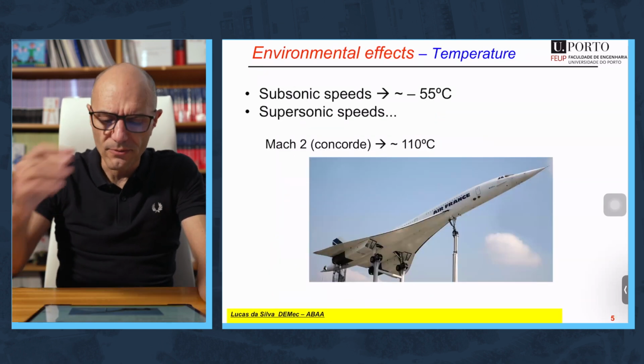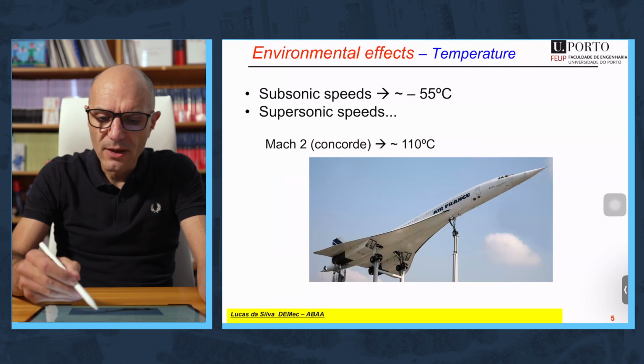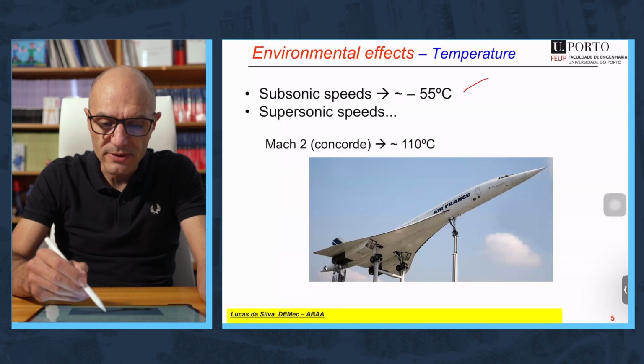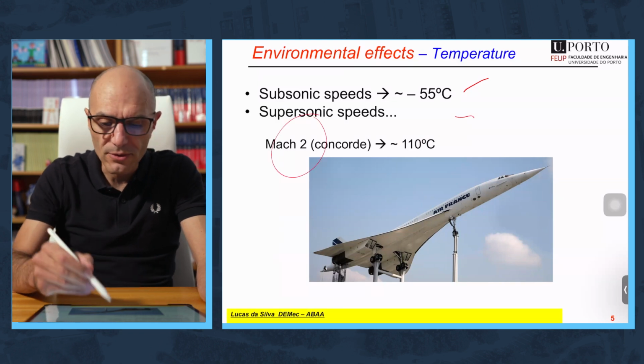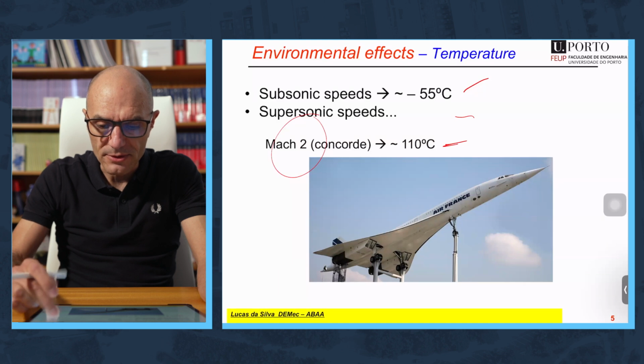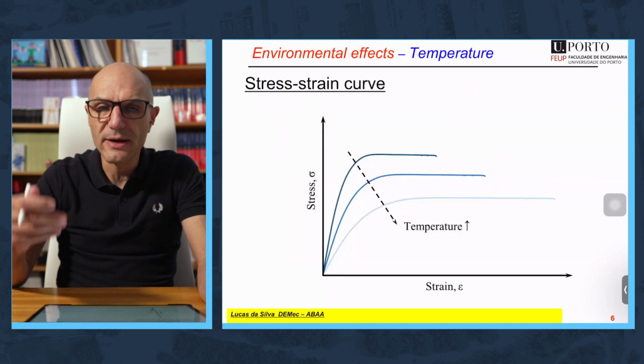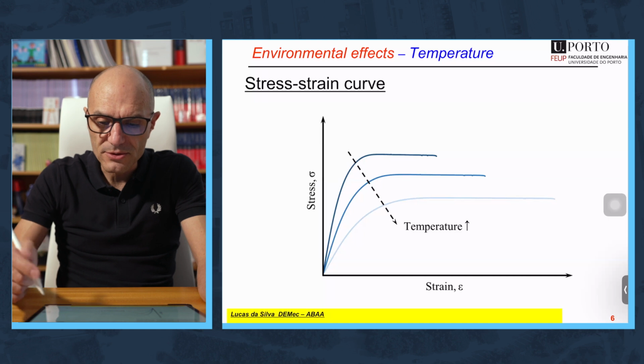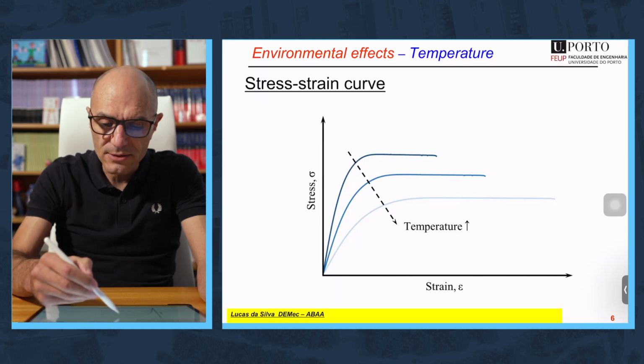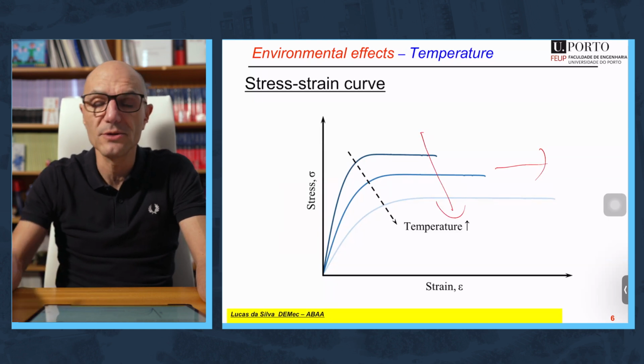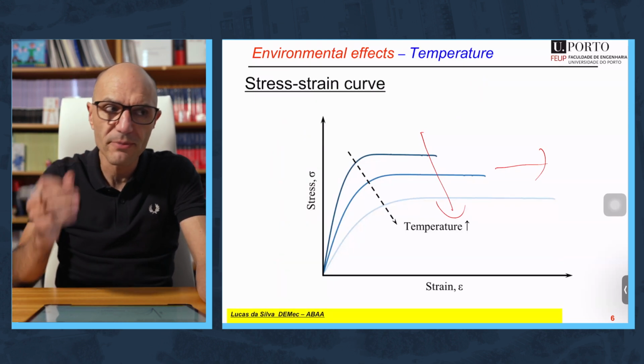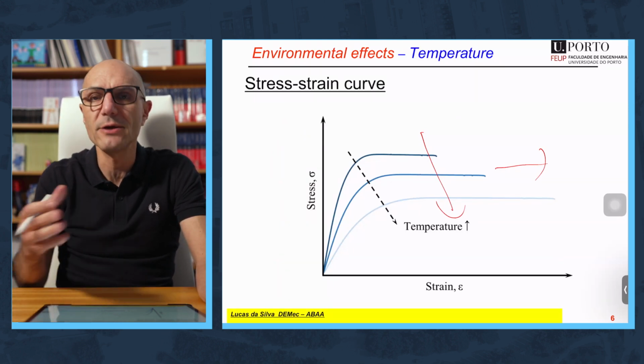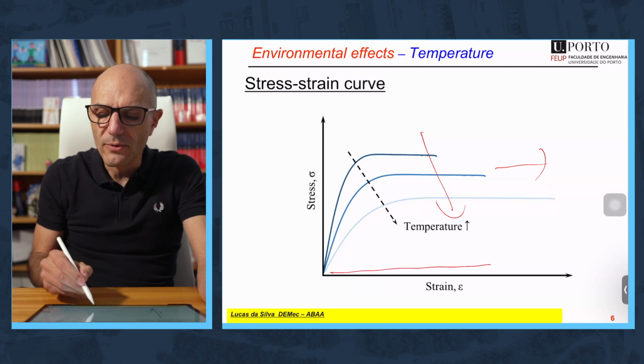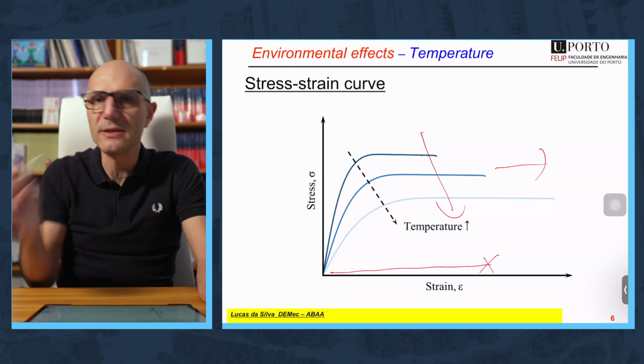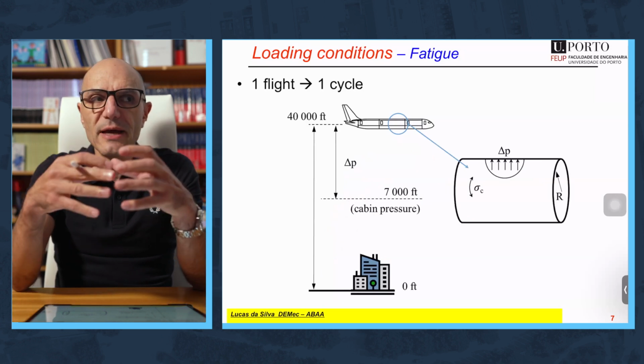Okay, the temperature we know, we have discussed that previously. When we go at subsonic speed, we have very low temperature, but if we go at supersonic speeds, for example, Mach 2 in Concorde, we can reach this temperature. So it's important to determine the adhesive properties when you have temperature fluctuations. And we know that as the temperature increases, the strength decreases and the ductility increases. Again, a bit of temperature is not bad because we get a higher ductility. But be careful, we cannot go above the Tg because then we lose completely the strength. So that's for the environmental factors.